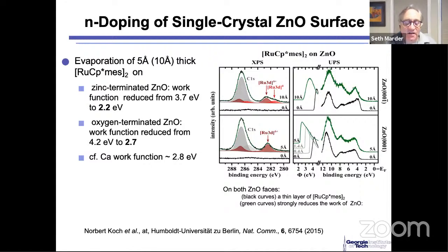So here's an interesting experiment that was done by Norbert and his colleagues, and I'm not going to go into all of the motivation for why they chose to do this. What they wanted to do was make a hybrid LED device where they were going to generate the excitons in the device in zinc oxide, and then ultimately deposit a highly emissive molecule on top of that. So they would try to generate the excitons in the zinc oxide and then have energy transfer to a material sitting on top of that.